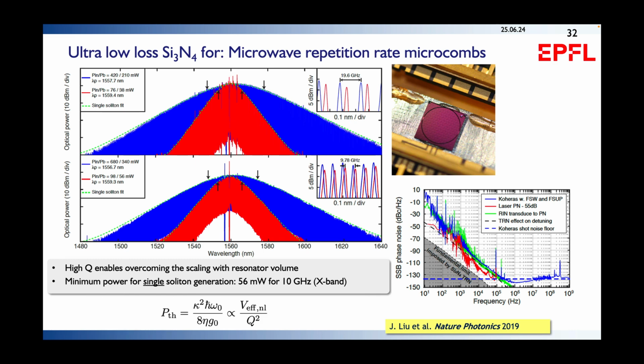So this is an example of a silicon nitride K-band and X-band generator. So it puts out streams of solitons at 10 gigahertz and also generates upon detection actually a reasonably low phase noise microwave here that comes in at minus 135 dBc per hertz at 10 kilohertz offset. So you can use them directly actually as a low noise microwave generator.